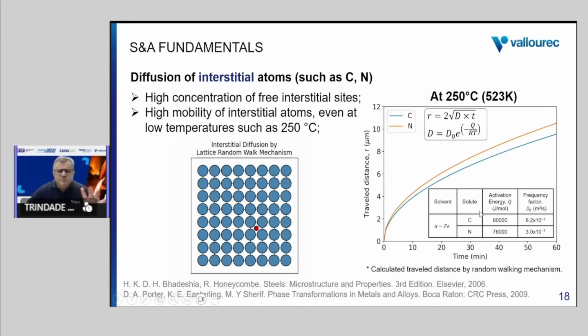If you make some simulation and pay attention to the interstitial atoms in steel, such as carbon and nitrogen, you can see that indeed at 250, 1 hour, those small elements can really have some mobility in the crystal structure, about 10 micrometer diffusion distance. And this is enough to reach the dislocation core and saturate those dislocation cores. So this is one important point.